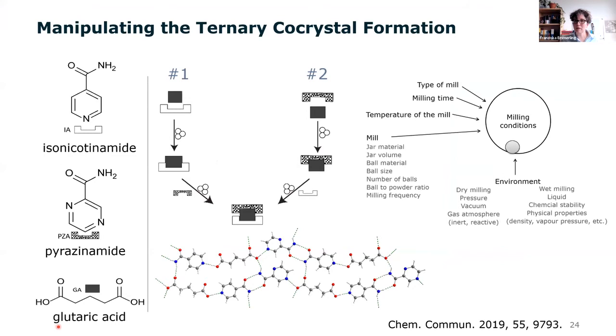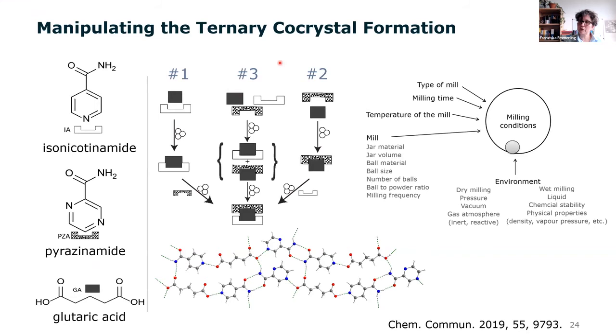We can also make ternary co-crystals, as I just showed before in our competition reactions. You can see here a ternary co-crystal consisting of pyrazinamide, isonicotinamide, and glutaric acid. And we knew from lab experiments that it's possible to form first the binary co-crystal and then add a third component and have the ternary co-crystal. We were wondering whether the third way is also possible, so directly mill together all three and see how this reaction performs, so which intermediates can be formed during the reaction. I bring up the milling condition picture here again, because in this case, we were looking at the milling frequency and the influence of the milling frequency on the reaction.